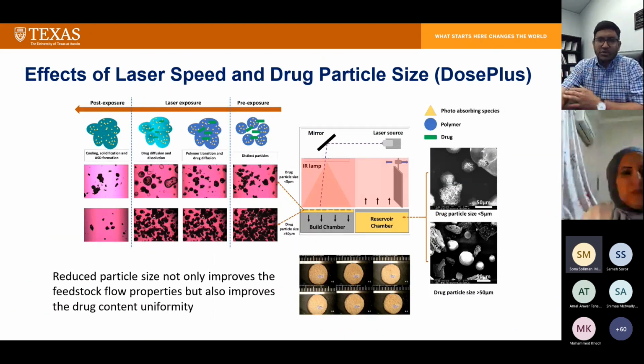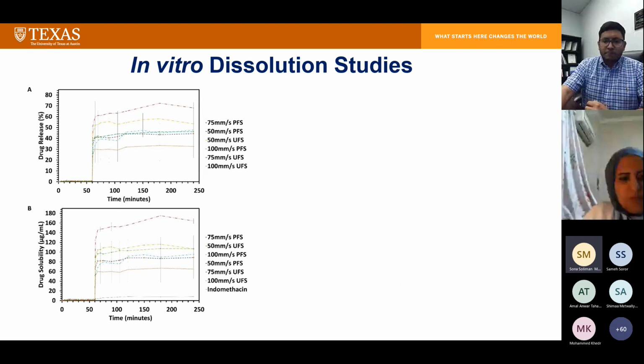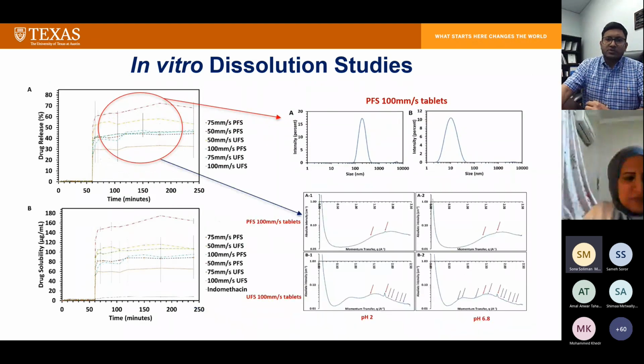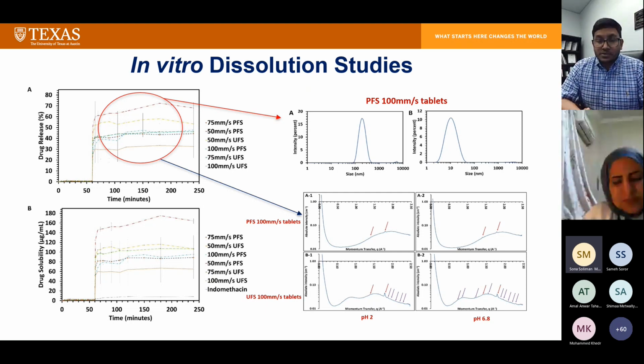So we continued doing more investigation. We looked at the effect of laser speed and drug particle size, and by looking at all the examples, what we found was that our Dose Plus was really a viable option to not only produce amorphous solid dispersion, but also maintain its amorphous state even during supersaturated condition-based dissolution studies. From this study, as can be seen, when we drew the sample from the dissolution vessel in a highly supersaturated condition, there was no evidence of recrystallization.